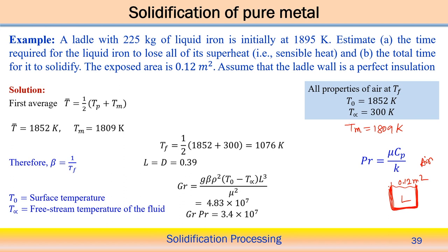First, the time required for the liquid iron to lose all its superheat. In this case we need to consider the average temperature between the peak temperature and the melting point temperature. The average temperature here is 1852 Kelvin, and TM is the melting point temperature. We can then do the other calculation, the film temperature TF, which is half of the sum of the average temperature, 1852, and the air temperature. So the temperature scale runs from TP to TM, the average temperature T bar lies in between these two, and T infinity is the air temperature.